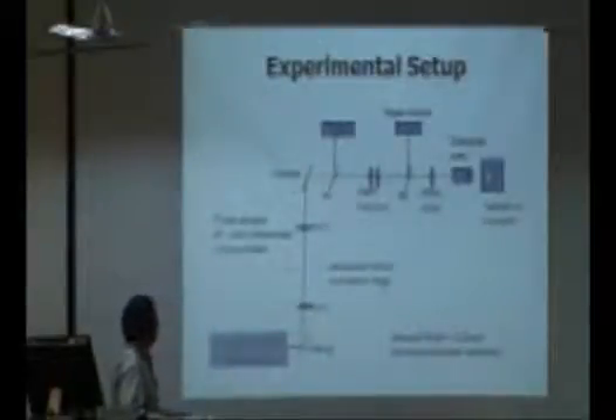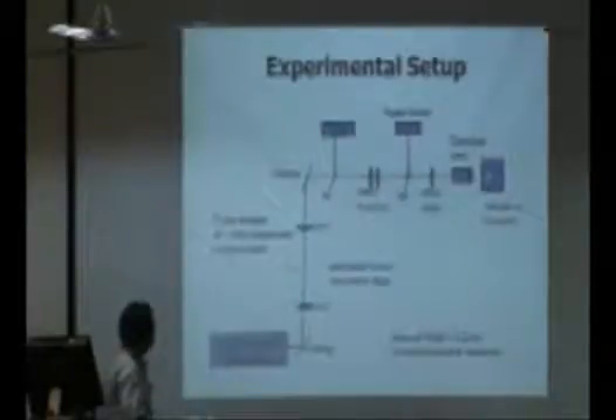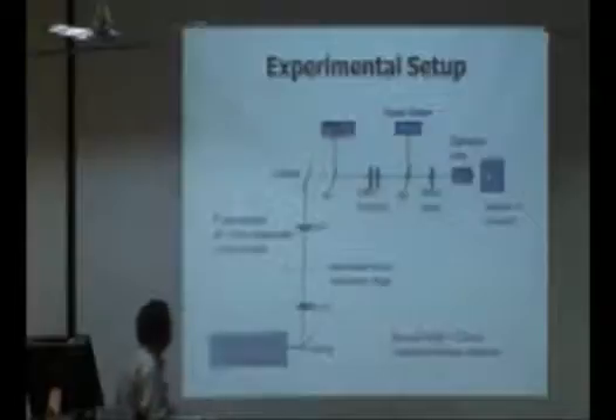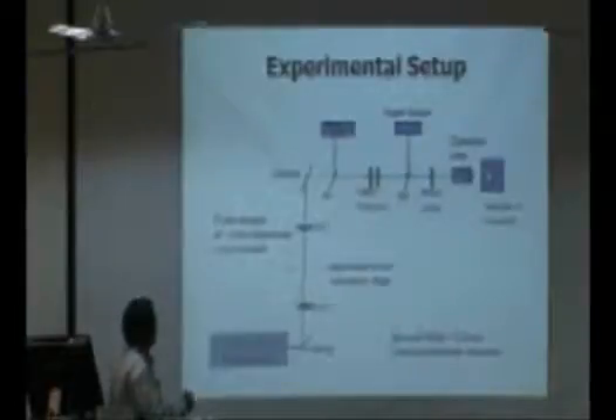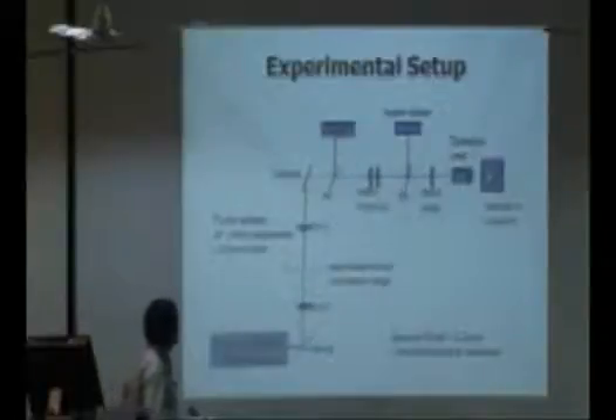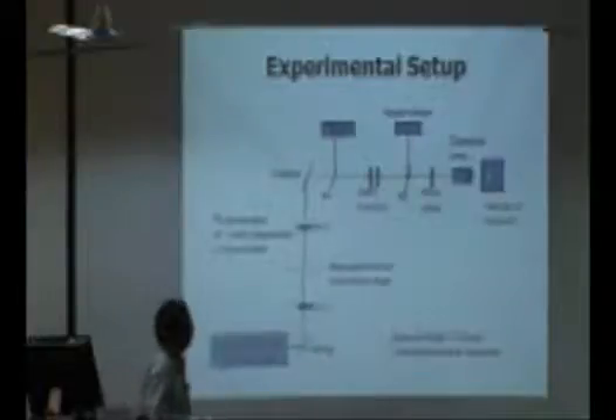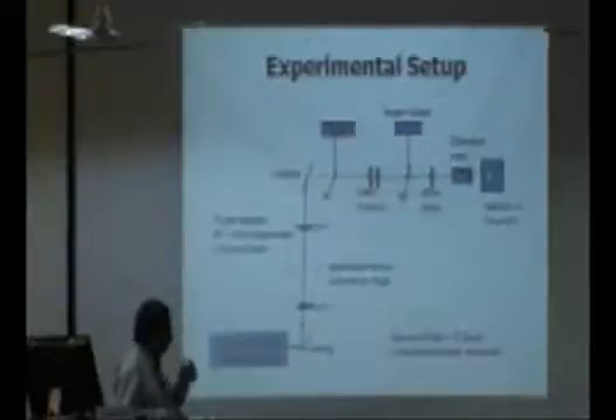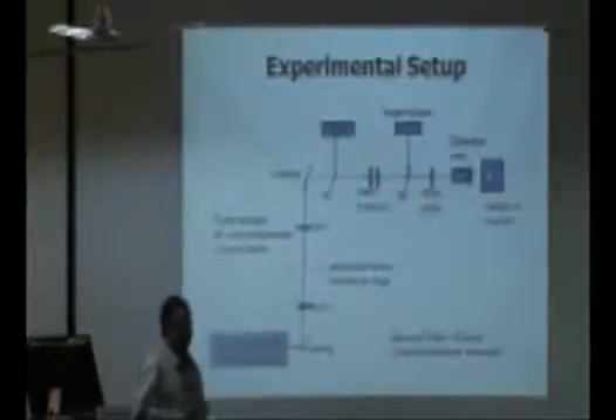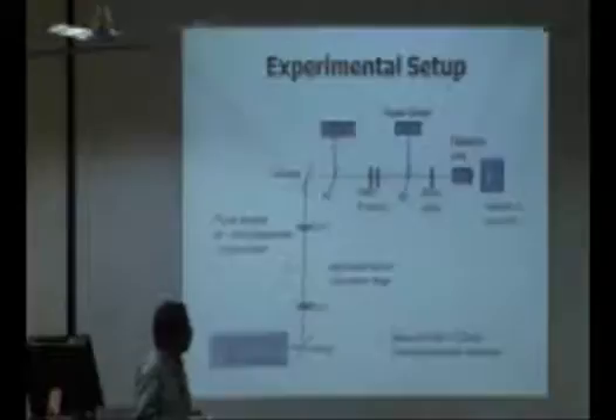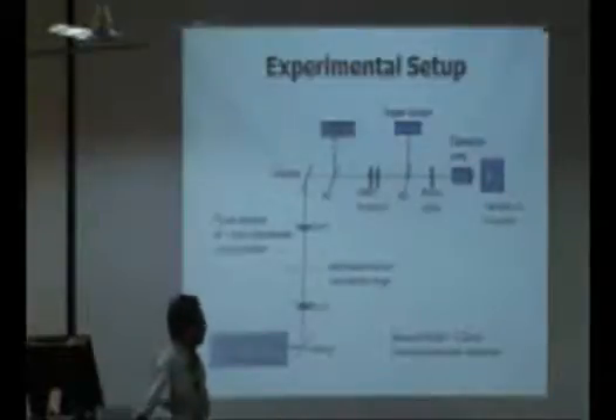So this is the typical setup to reduce bi-exciton and multi-exciton excitation. We used a 4F zero dispersion compensating pulse shaper. That reduces the spectral width, and then we also use circularly polarized light to eliminate the multiphoton excitation, especially the bi-exciton resonances.